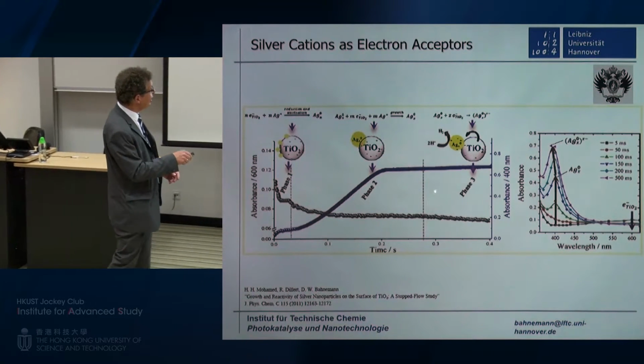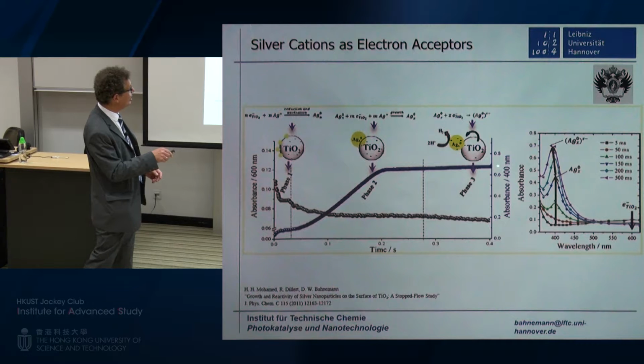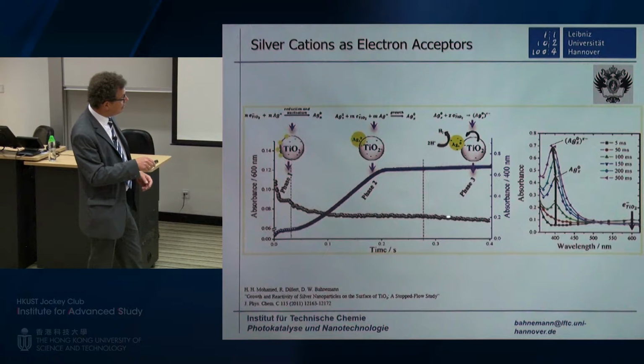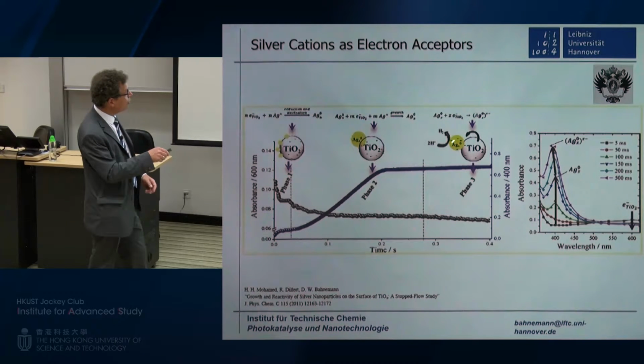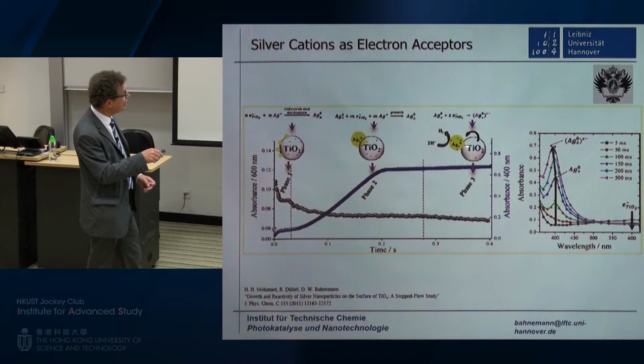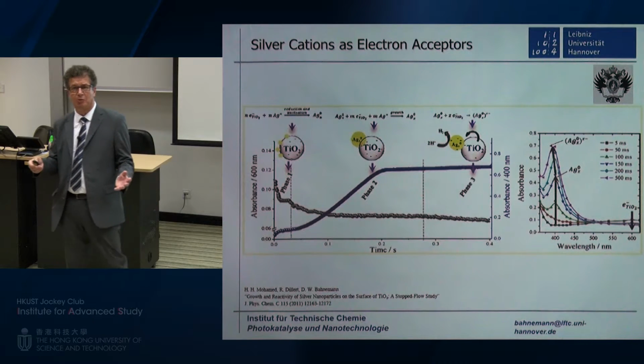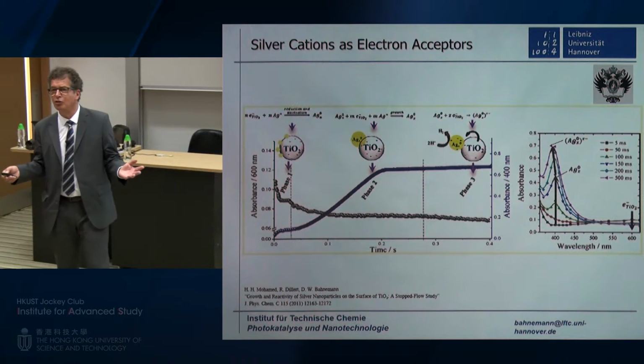And finally, the silver clusters are all nicely formed, but electrons are still used. And what is happening here is now you have a catalyst on the surface of the TiO2. This catalyst is needed for transfer of 2 electrons to protons to form hydrogen. So hydrogen is only formed, and we know this from other experiments, and the whole world knows it.